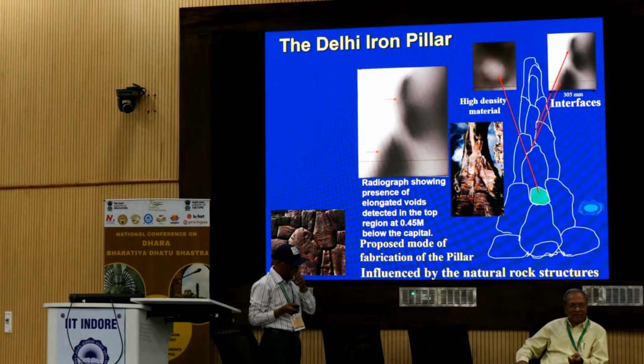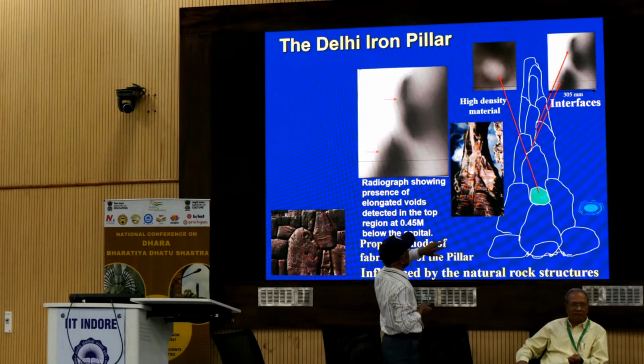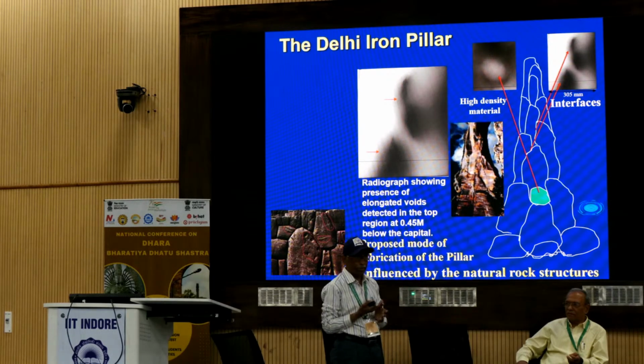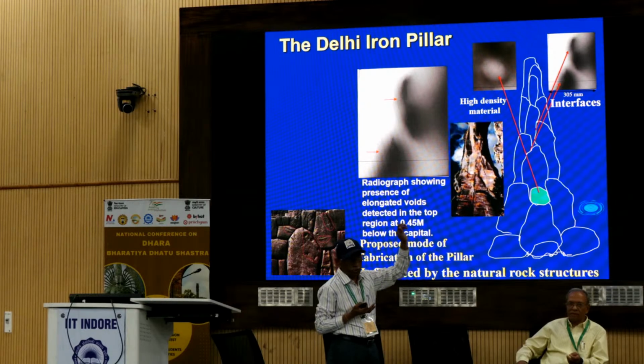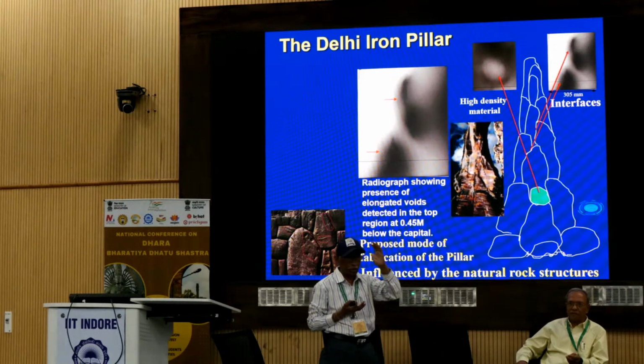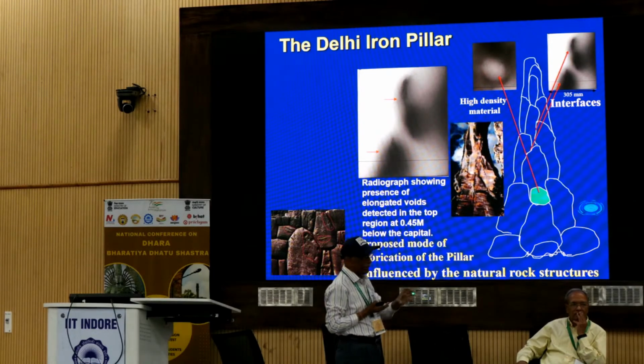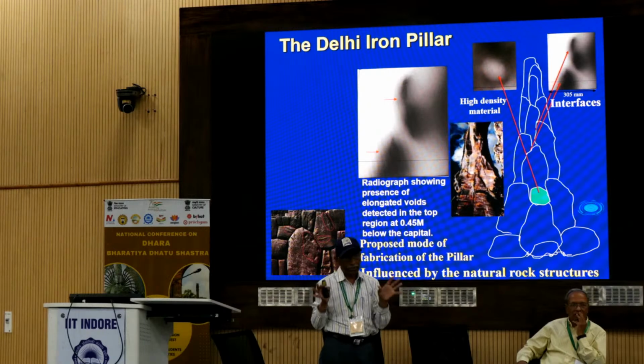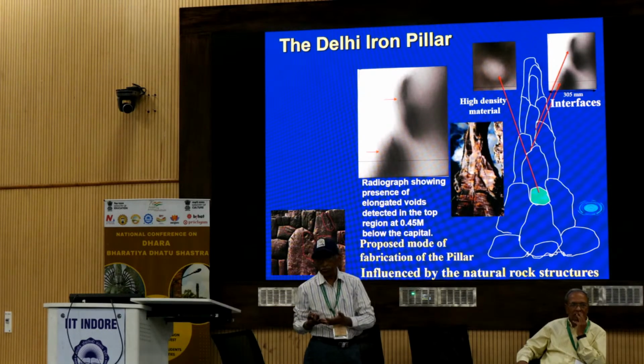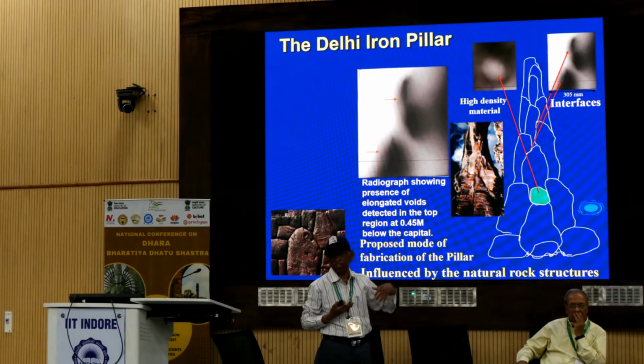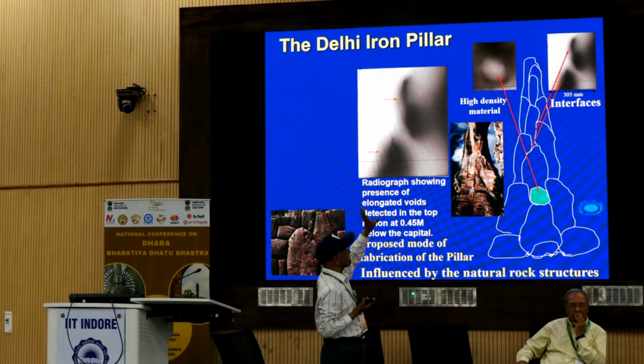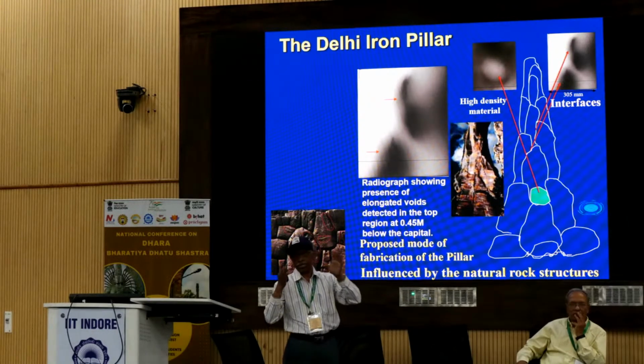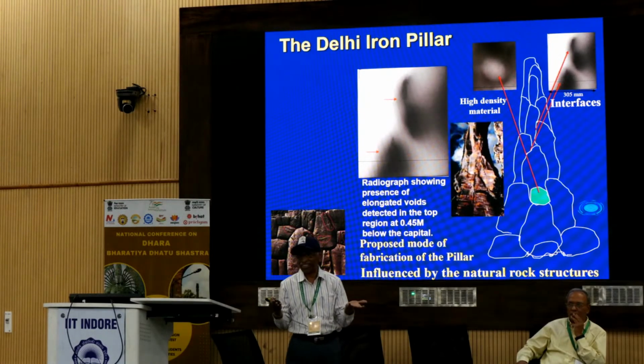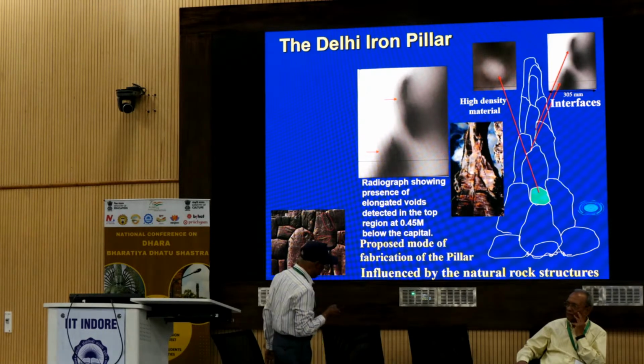That is one aspect. And then in one of the regions of the iron pillar, you can see that the white contrast in the radiograph means the metal is heavy compared to the remaining regions, and that's why X-rays are absorbed in that region, because X-ray absorption is directly related to the atomic weight. So we believe that there is some material which is denser than the iron. Only that much we can tell. But further, it is only a guesswork that it is silver or gold. So normally gold is used in many places, even in bronzes, etc. So we believe that it is gold which is there inside the iron pillar. If it is a void or something, you will see dark. So that is another point which I would like to say.